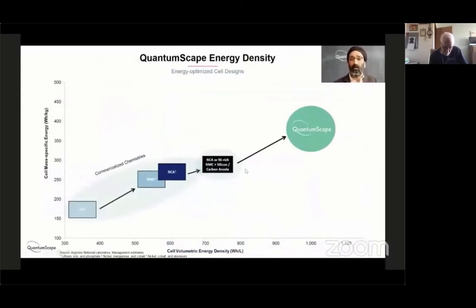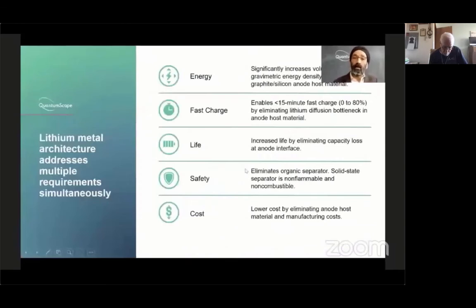This is a substantial step up in energy density. The real additional win here is that in addition to energy density, you also, in one fell swoop, solve the fast charge problem, because it turns out that the main limitation to fast charge is the diffusion rate of lithium through those carbon particles in the anode. And if you take away the carbon particles, you take away that diffusion bottleneck. And now you can charge the battery as fast as the cathode can deliver lithium ions to you. It turns out you can now get a 15-minute charge, which you cannot do with conventional batteries.